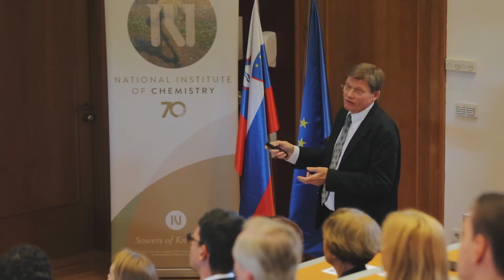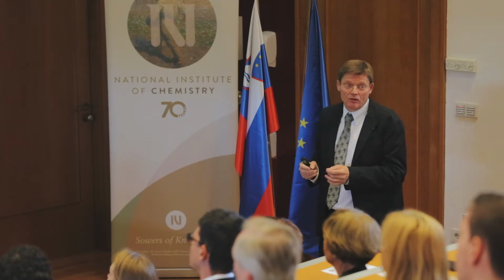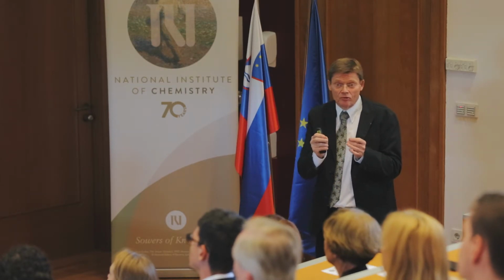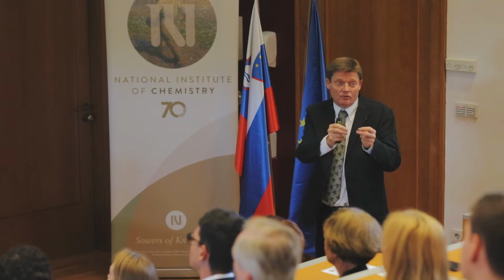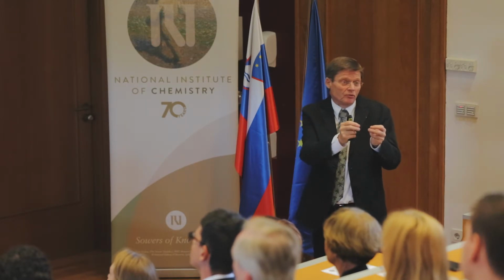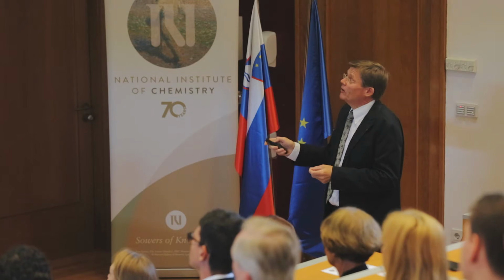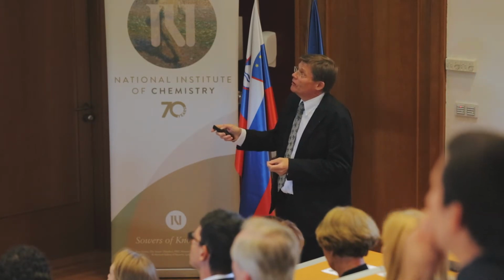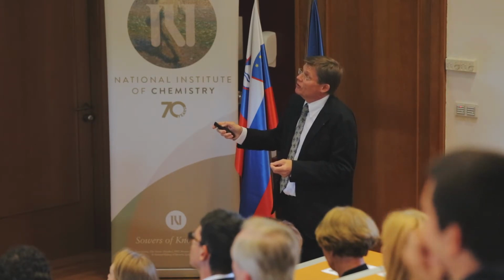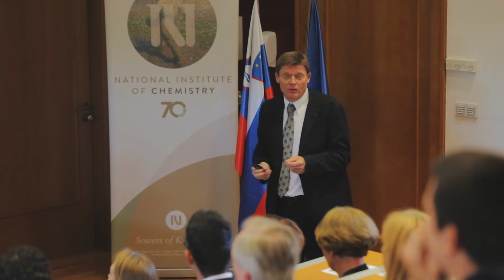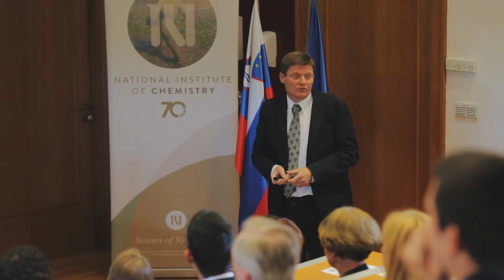This is the blue and the red phase. Both of these cannot store lithium. Lithium storage means lithium plus and the electron. In many phases it cannot do both. But there may be a phase which can store the electrons, and another phase that can store the ions only. You put them together, you get storage.